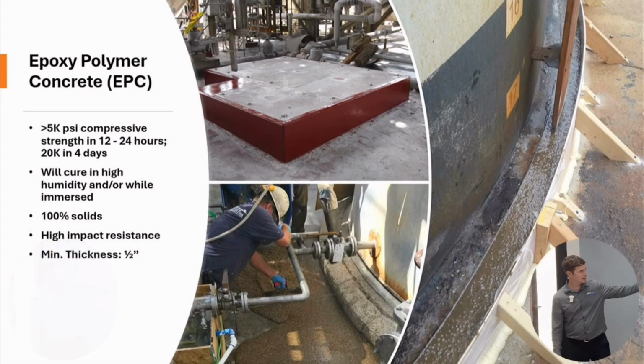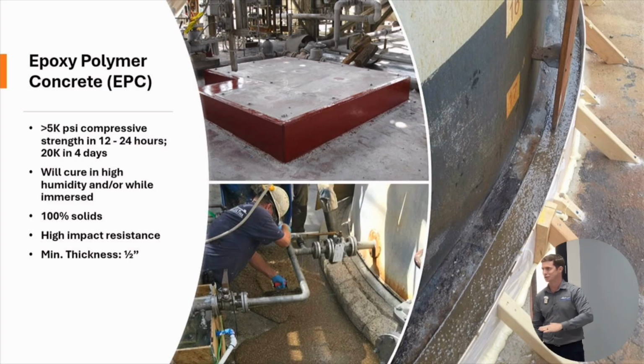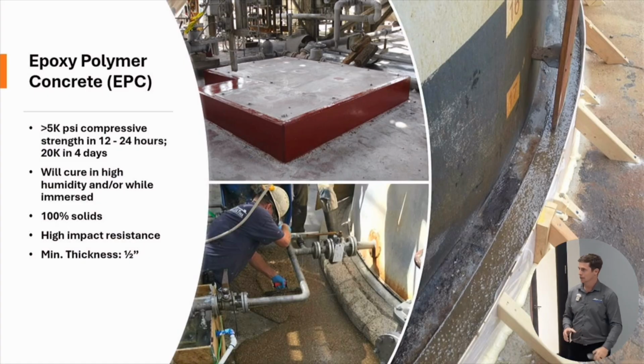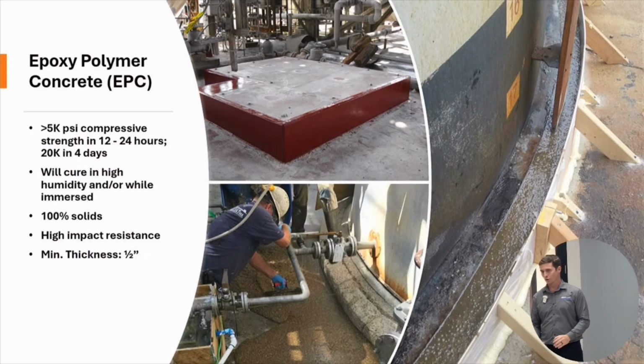More on the polymer concrete. In areas around a tank, maybe you've had chemical corrosion, and I mean, this tank was actually corroding from the outside in because whenever they had excursions, it was a black liquor, it was a tall oil area, so black liquor was getting under the tank and corroding it from the outside in. So they had a couple of choices. One choice was to tear out the concrete. To replace it with concrete, you need 4 inches. So that's a lot of jackhammer and a lot of tearing it out. Or you could use a material that could be primed, and then you can apply it at a 1/2 inch. So the minimum thickness of the EPC is a 1/2 inch. You can do a lot with that material. It's chemical resistant, and then you can go on with a more chemically resistant top coat.